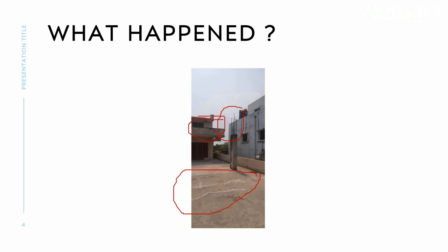I haven't even taken clear pictures of the slab, since the customer was so concerned about his building, so I was not able to take more pictures. Because of this exposed reinforcement, the structure was in a very bad situation. I suggested removing all this concrete, casting new column concrete, and removing the reinforcement too, since it is totally corroded. For the slab, I suggested checking whether the reinforcement under it has been exposed to corrosion or is still good.